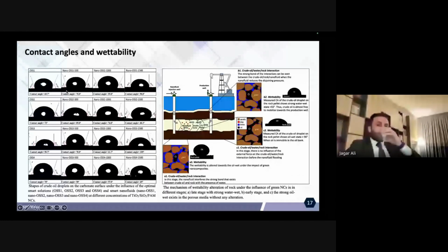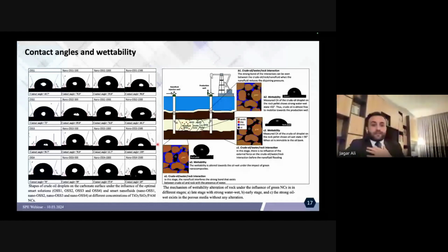These are some screenshots of the crude oil droplets on the surface of the rock. So, for example, here the contact angle is higher than 100. It's 109, sorry. We can see it here. So it's obvious that crude oil is highly attracted by the rock and it's immovable. But in the upper one, the contact angle is less than 90, for this condition about 48 degrees. It means, and it's obvious, the oil is almost free to be moved.